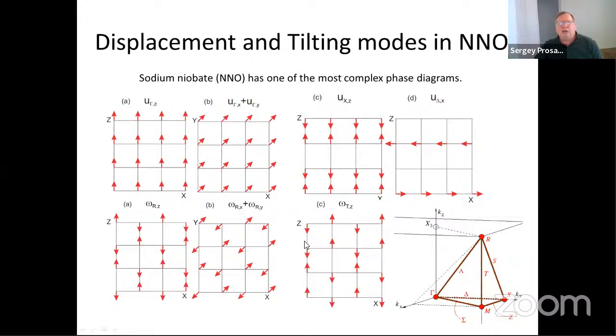Now I want to switch to sodium niobate. So sodium niobate is probably the most complex antiferroelectric known, and it has very many phases, antiferroelectric phases and ferroelectric phases. So this is a very complex material, and I show on this slide the modes which are common for sodium niobate. These modes can be polar, like the first two, antipolar, like the second two, and antiferrodistortive, like the modes at the bottom.